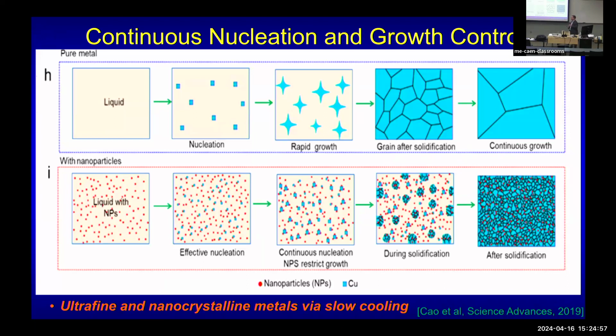Naturally, it's free growth theory: I grow, I win. They also release latent heat and kill all the nearby competitors, which get smashed away by the released latent heat. So they just become big grains. But in nanotechnology, first of all, we need to rely on the nanoparticle self-dispersion. Once you disperse well, in the first wave some nanoparticle-nucleated grains form, some big, some small. But when they want to grow, the nearby nanoparticles pin them down and block them.